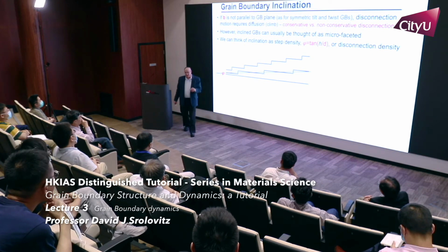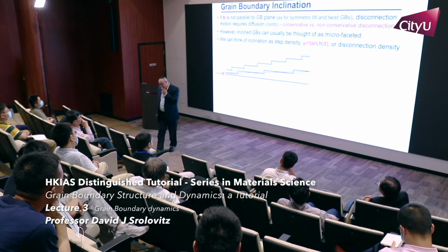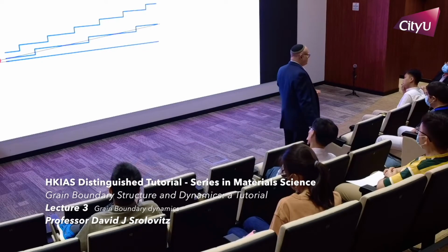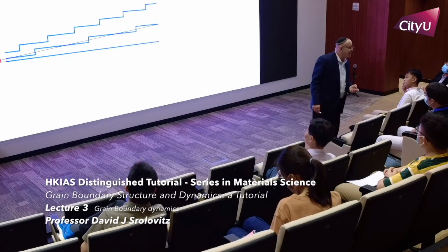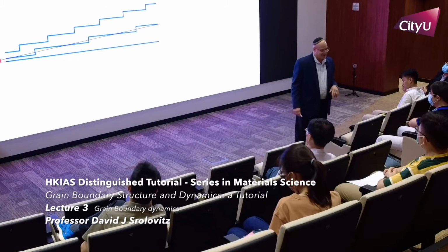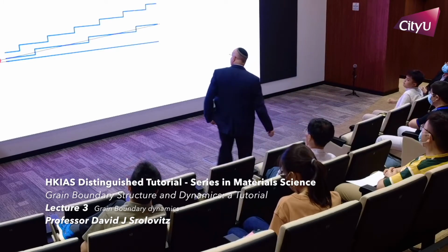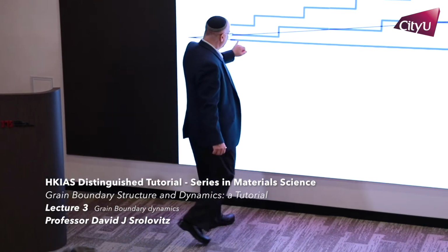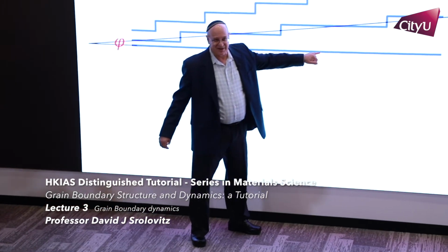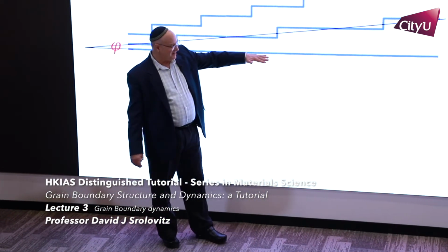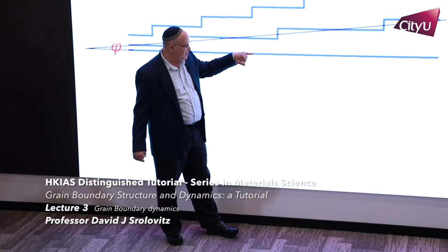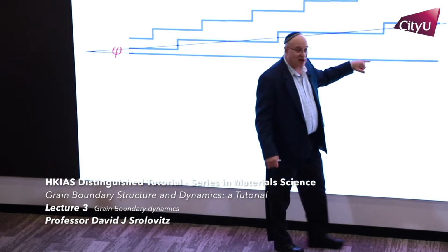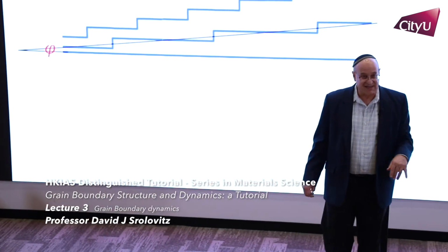Now, up to now, I've talked all about the misorientation. We talked about Burgers vector and step heights, right? But that comes from the DSC lattice, and that only depends on the misorientation. Now, let's say this is a grain boundary. If the Burgers vector is parallel to the grain boundary, then the disconnection can just glide along it, just like a dislocation slip plane.